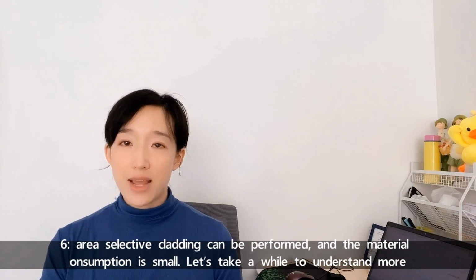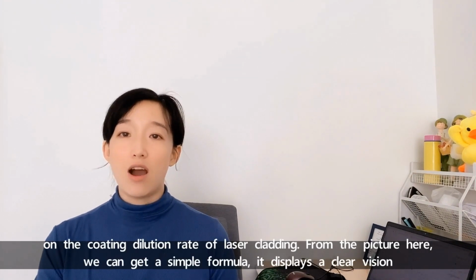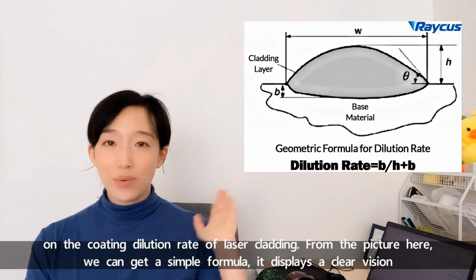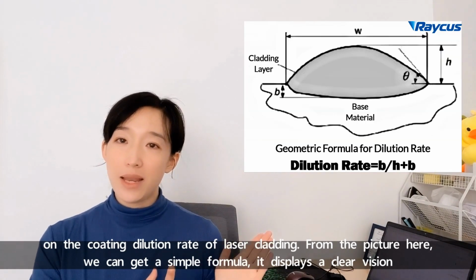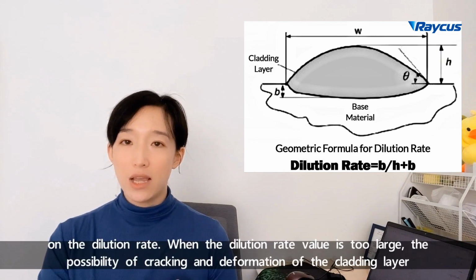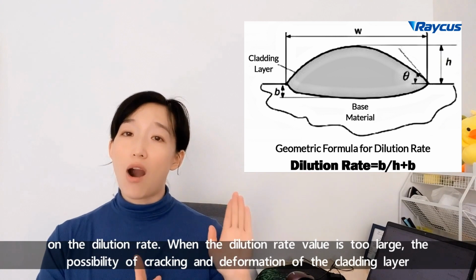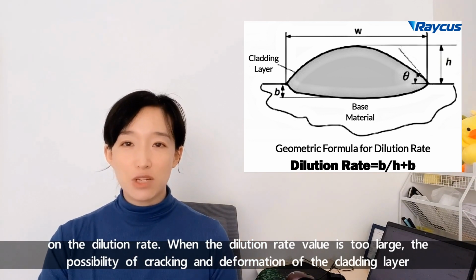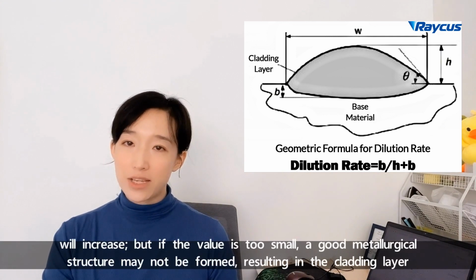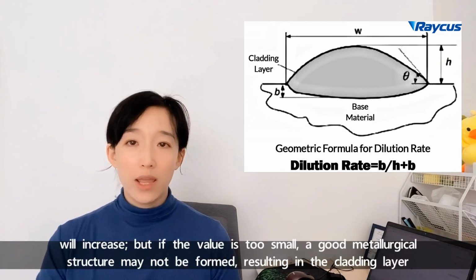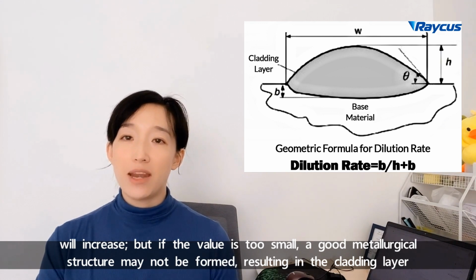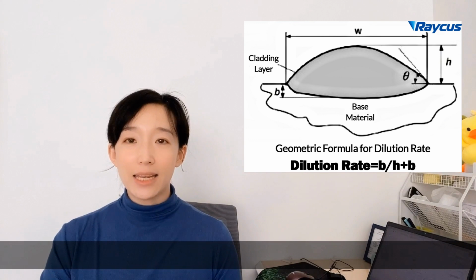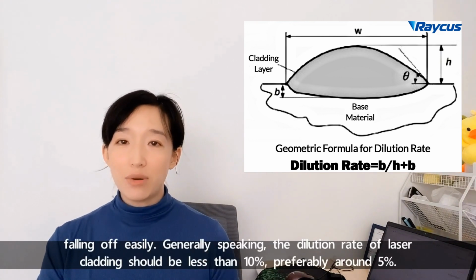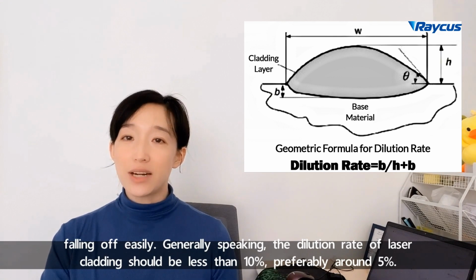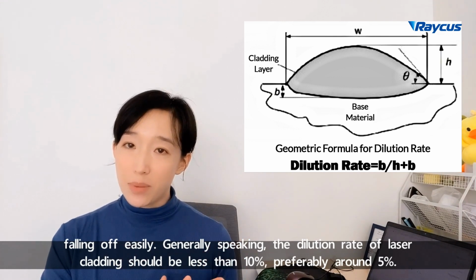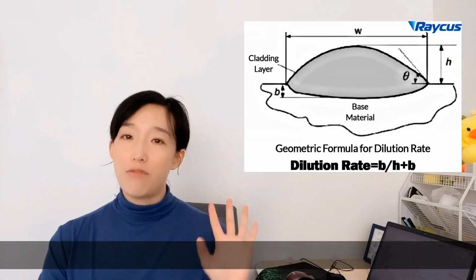Let's take a while to understand more on the coating dilution rate of laser cladding. From the picture here, we can get a simple formula. It displays a clear vision on the dilution rate. When the dilution rate value is too large, the possibility of cracking and deformation of the cladding layer will increase. But if the value is too small, a good metallurgical structure may not be formed, resulting in the cladding layer falling off easily. Generally speaking, the dilution rate of laser cladding should be less than 10%, preferably around 5%.